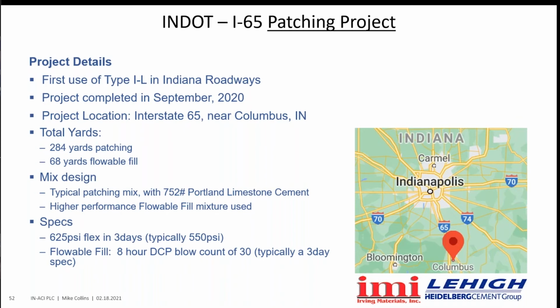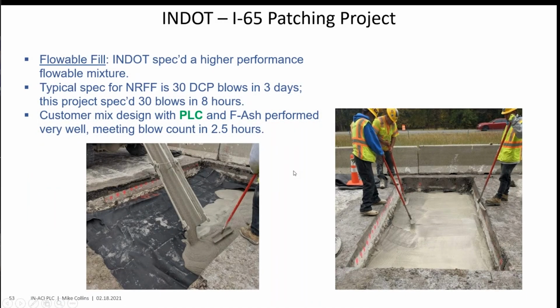Some specs that were a little interesting was 625 PSI flex in 3 days for the patching, and the flowable fill had an 8-hour blow count of 30, and typically you might see that as a 3-day count. So just to take a look at that, the flowable fill mix actually performed very well. One of the things that kept this project going in a real timely fashion was that IMI was allowing up to 8 hours for this material to set before they could start the patching. This flowable fill, which was a combination of PLC and fly ash, actually reached blow count again in 2.5 hours and allowed that project to speed up a bit.